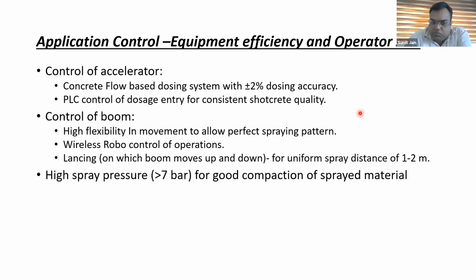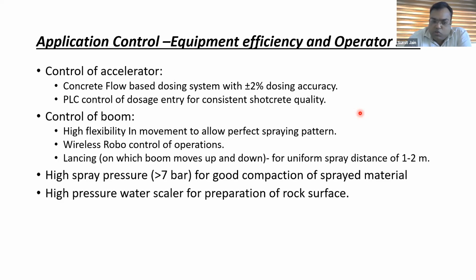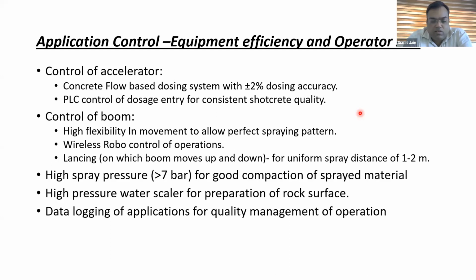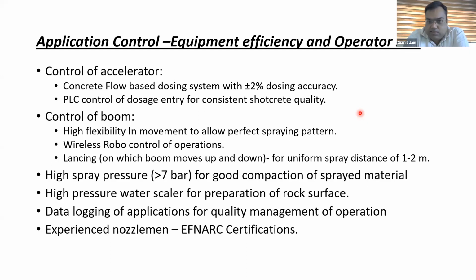Then we should have a very high spray pressure up to 7 bars for good compaction of the sprayed material, else you get a poor compaction in the shotcrete. We should also have a high pressure water scaler on the machine. This is used to prepare the rock surface. Sometimes there are certain hydroscaling requirements at the tunnel wall. So with a high pressure, you can chip off certain loose rocks attached to the substrate. And then of course, data logging of applications is a must to check what we are actually doing inside the tunnel. And last but not the least, an EFNARC certified nozzleman is the best way out to ensure that the operator is really skilled.